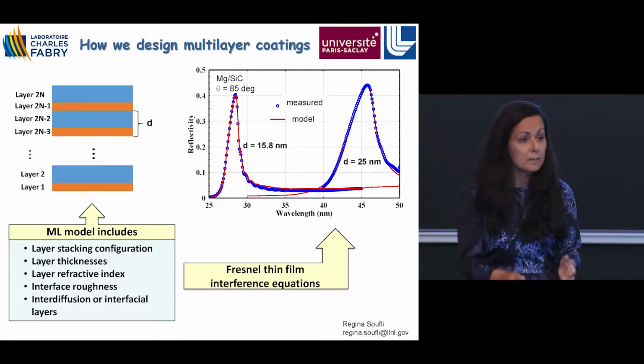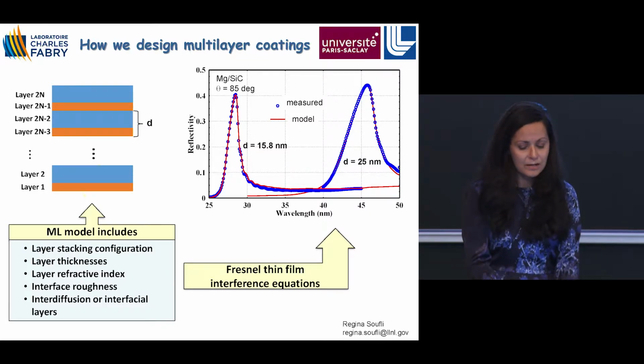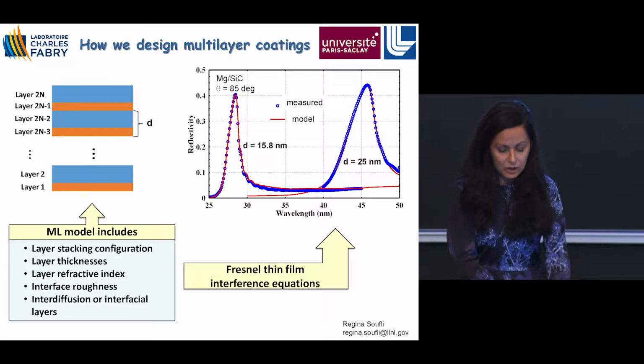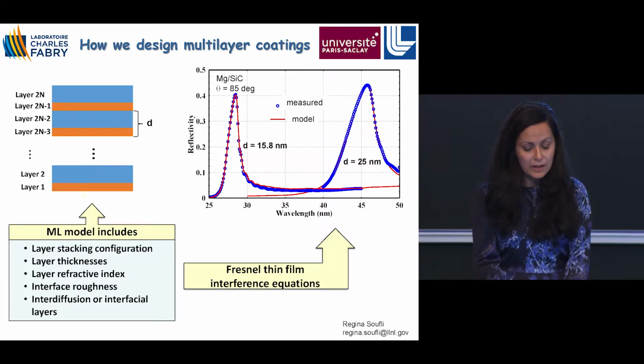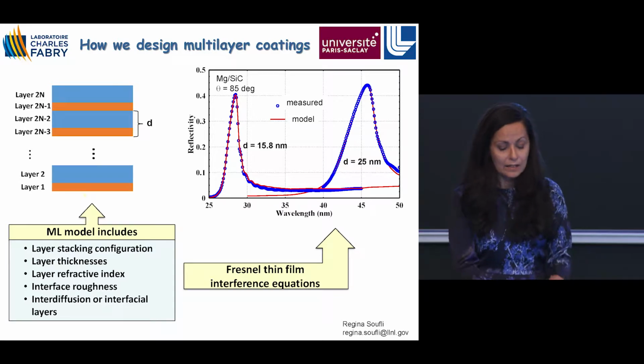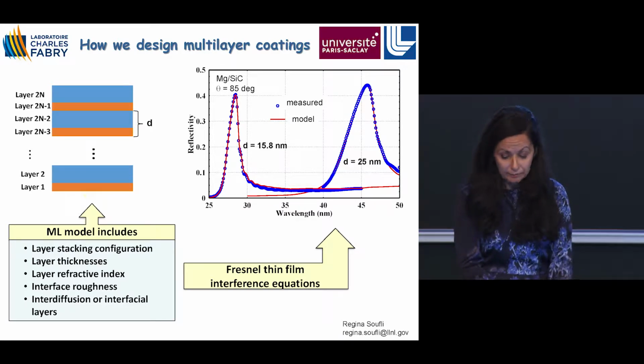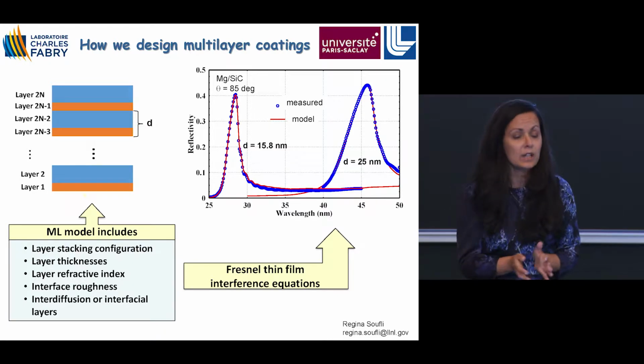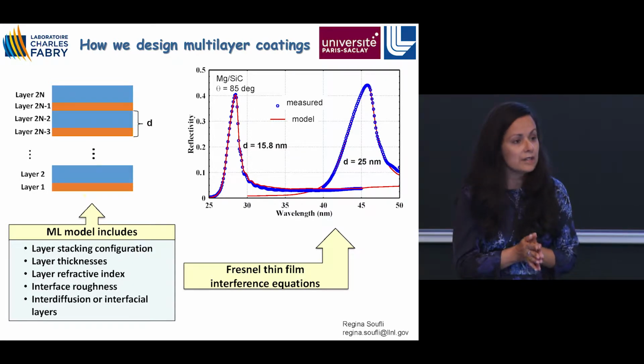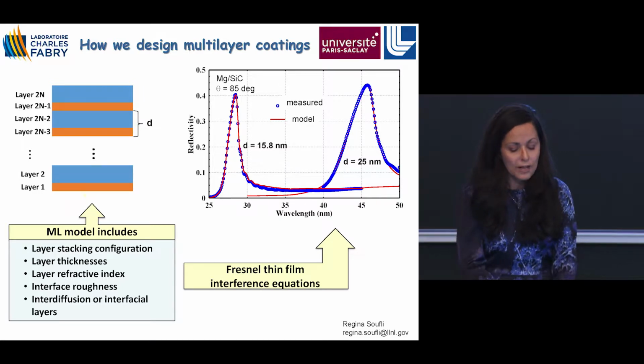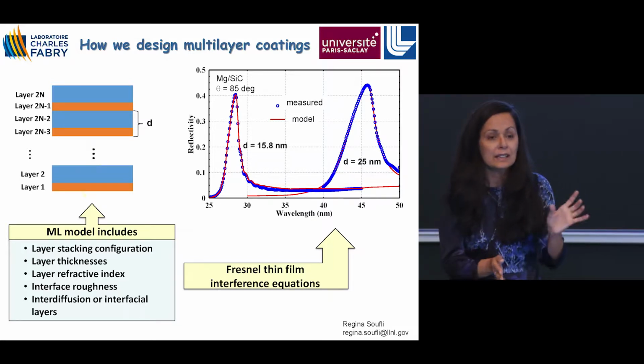So pick two materials based on the available refractive index values that you have, that have good contrast in this photon energy region, in this wavelength region. And then adjust the ratio between the two materials to get the right peak reflectivity and the right bandwidth. I should mention here, it's very important, lots of multilayer coatings operate in the region below the absorption edge of their constituent materials, because there, this material that is part of the multilayer has low absorption. So it can have very good contrast with the other material and produce high reflectivity. So multilayers typically operate near absorption edges.